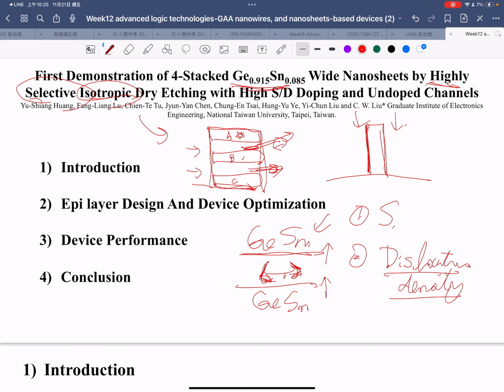Usually, if the dislocation density is pretty low, the other problem is the selectivity is also low, because I think the germanium and tin layer etching selectivity is pretty large, but the dislocation between silicon and germanium is pretty large. So if we want to solve the problem, you have to use silicon germanium, and the germanium concentration should be low. If the germanium concentration is low, the etching selectivity will be low. So this is a big problem.